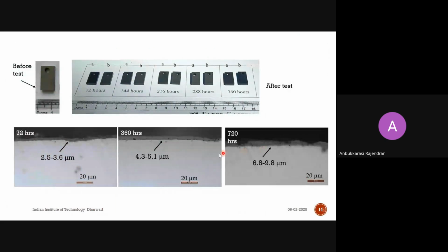Okay, so the optical micrograph can give other information. This is one of the corrosion samples on which I carried out the corrosion test for one of the DST projects. After it was exposed to a certain temperature at different pressures, I could see some layers formed at the surface, so I wanted to see them first under the microscope. These numbers show the time of exposure of the sample in the particular environment. With increasing exposure time, the layer thickness gradually increases.